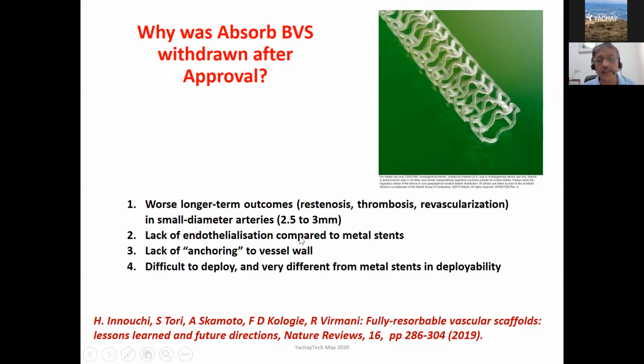And endothelialization is also important for fully degradable stents, because if it is not endothelialized, then the degrading stent will actually put out pieces of the stent into the blood vessel, which is not at all desirable. It is a big problem if that happens. So endothelialization is key to the performance of fully degradable stents. And also what is called lack of anchoring to the vessel wall. So the material that expands with balloons also shows a little bit of recoil.